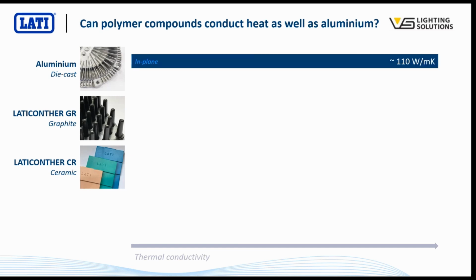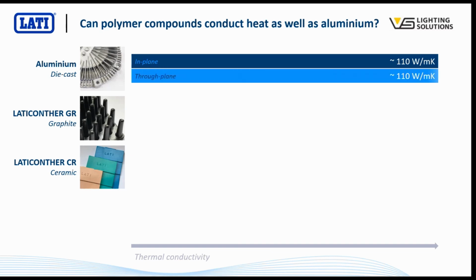So for aluminium, you have a thermal conductivity in plane, so along the length of a part, of around 110 watts per meter Kelvin. This is for die-cast aluminium. And because aluminium is an isotropic material, it's got the same properties in all directions, so the thermal conductivity is exactly the same through the thickness of the part as it is along the length of the part. That's not the same with thermally conductive plastics, though.